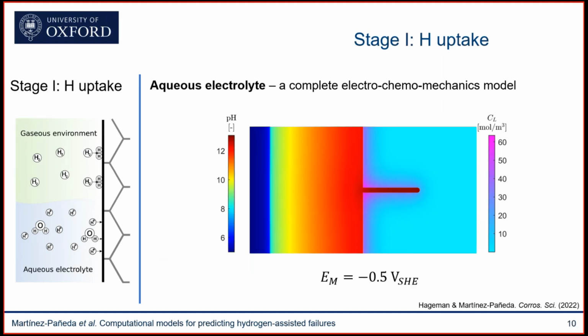And this is the kind of representative result that you'll get. Here I'm plotting on the electrolyte the variation in pH. You can see that it changes quite dramatically from the bulk pH to the inside of the crack. And here you see the uptake of hydrogen inside of the metal. This is, of course, obtained for a given time, after 10 minutes of exposure to a hydrogen-containing environment, for a given applied potential, for a given fluid velocity, for a given material. But again, with these virtual platforms, we can change any conditions that we want, and we're able to quantify the hydrogen uptake for a given environment.